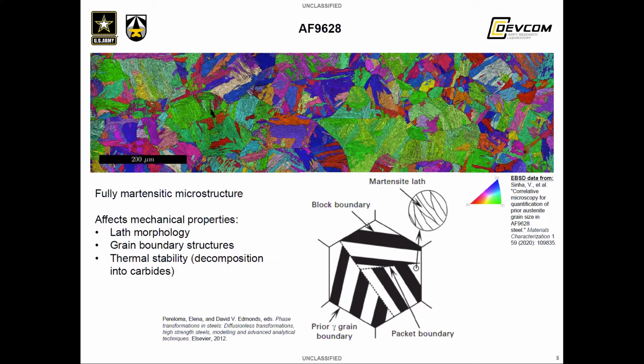You can make out in this material many of the prior austenite boundaries visually. One common result of the martensite transformation in some steels is that the austenite grain boundary structures are often very well preserved. Within a region of a prior austenite grain, the martensite laths are grouped into packets of laths that have the same habit plane of formation. Within a packet, you have blocks of similarly oriented laths. A depiction of these different structures is shown there at the bottom right.